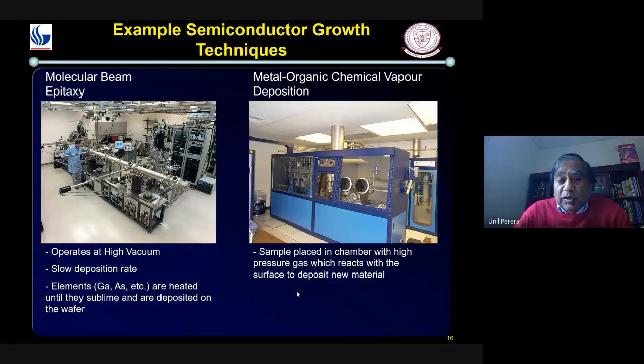And so most of our detectors were grown by what is called MBE, molecular beam epitaxy, or MOCVD, metal organic chemical vapor deposition. So MBE is very accurate, with very sharp interfaces, but cannot grow very thick material because it grows at 1 micron per hour rate. So you cannot grow hundreds of microns. But with MOCVD, you can grow much thicker material, so it is much faster, but the interfaces are not very sharp. But both need very high vacuum, MBE particularly, and they are very expensive systems.